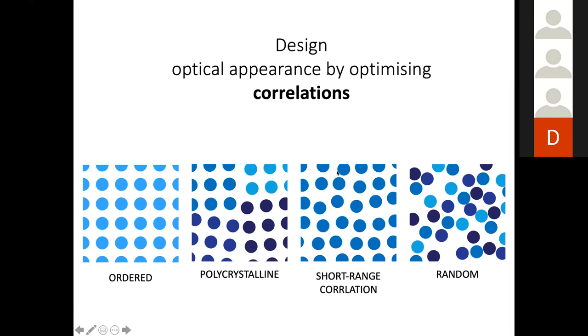You can also have intermediate correlation systems that are polycrystalline or short range correlation. I will show you a few examples in a moment, where you can actually obtain the same structural color. You can obtain structural color because the scale is comparable with the wavelength of the light, but the color is much more uniform, it's less angular dependent. And finally, when you use completely random structure, you can make white. If I have a moment, I will show you at the end of the talk.